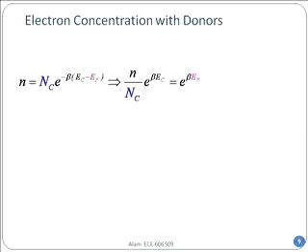So what I did here in the first one, you know this, that N is by definition the effective density of states, about 10 to the power 20 per centimeter cube, multiplied by that beta, which is 1 over kT, by the way. Anytime you see beta in this one, EC minus EF depends on where the Fermi level is. So you can rewrite it. You say NC e to the power beta EF on the right hand side, and you can flip the capital NC and EC on the other side.